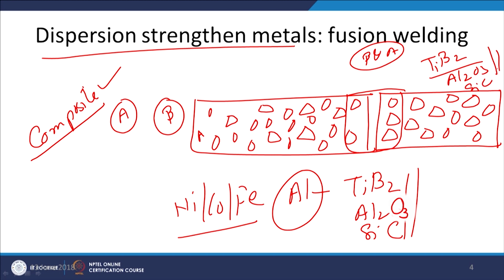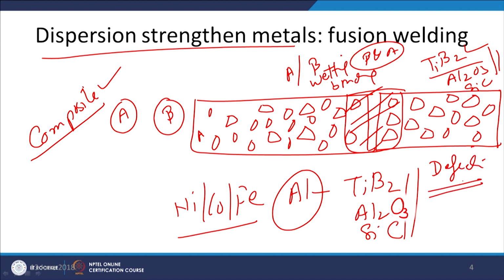So, these can be thermally damaged due to the external heat supplied for the fusion welding. This is one problem, thermal damage to the reinforcing agent. Second, since the metal matrix A may not be very compatible with the B, there can be various issues like wetting and bonding between them. So, these may be missing. So, poor wetting and absence of metallurgical bonding between A and B in the molten state can lead to the development of a number of defects in the weld joints. So, this is one of the issues as far as fusion welding is concerned.